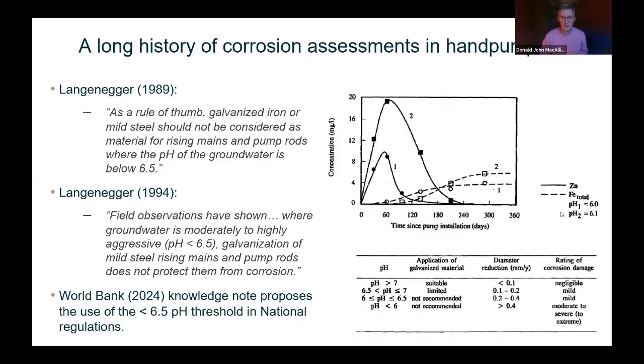Just before I get into that, I wanted to again highlight the work of Langenegger in the 80s and the 90s, where he did a lot of observations and experiments looking at how hand pumps corrode, and identified the pH threshold of 6.5 as a risk factor 40 years ago. The plots on the right here are an example of how, as the pH gets lower, the rate of corrosion increases. And he developed this risk classification that you can see in the bottom right-hand side.